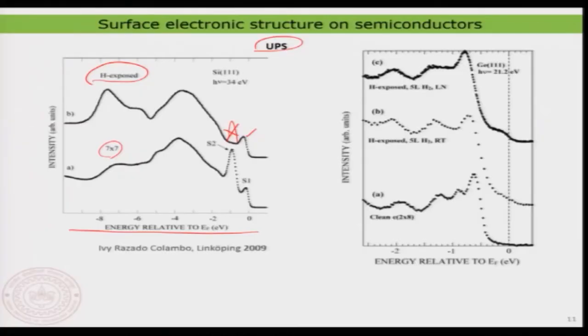I have one more example here, which is again a germanium 111 surface, also a very popular semiconducting material. You can see here a clean 2x8 reconstructed germanium 111 surface. Upon hydrogen passivation, you can clearly see some of the peaks are missing. This peak is missing. These two are the same spectrum; one is done at liquid nitrogen temperature and the other at room temperature. But you clearly see that one particular peak has vanished upon hydrogen exposure, which indicates that you have surface passivation and the surface atoms have now reacted with the hydrogen you exposed onto the surface. So that's the interesting thing.